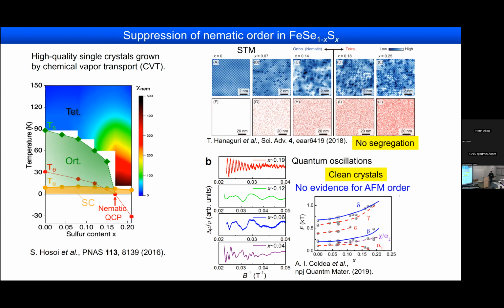Then this electronic nematic transition temperature of 90 Kelvin can be suppressed by using isovalent substitution. You can substitute selenium with the isovalent sulfur. And you can actually completely suppress the electronic nematic transition. And you can find evidence for nematic quantum criticality by the measurements of nematic susceptibility, which can be measured by using the elastoresistance technique. Okay? And what is important here is that we can grow quite high quality single crystals by using the CVT technique. And you can take a look at the STM topographic images in which you can find the position of sulfur atoms. And this sulfur is uniformly distributed.